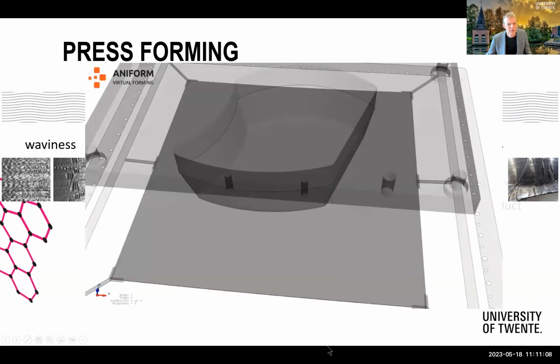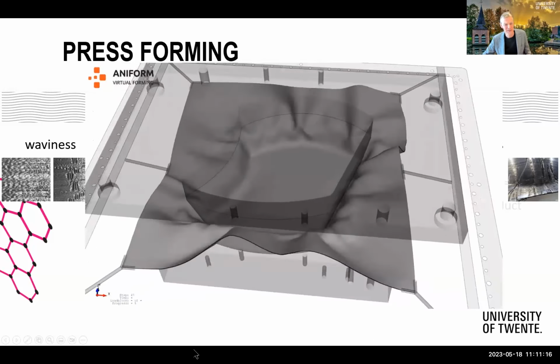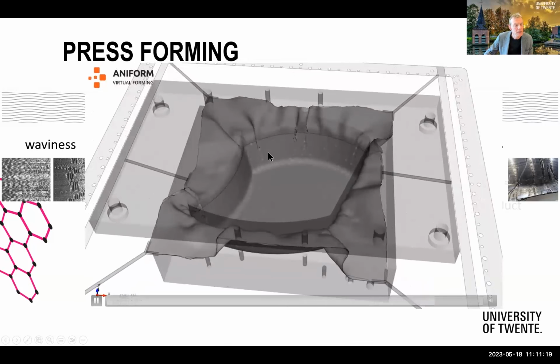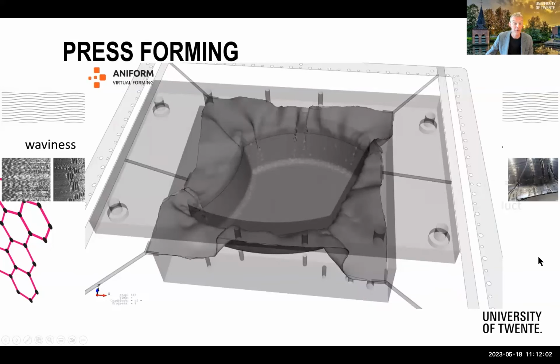Well, of course, that is very much part dependent. So here's, let's say, a fruit basket, a composite fruit basket. You always wanted to have one like these, but here you can obviously see quite severe wrinkles in the flanges of this shape. In forming software, you have the ability to change easily the size of the blank, the shape of the blank, the laminate supports, etc. And you have the relative ease of changing the geometry of your tooling to get a product without these nasty defects, which actually permits using the products you've manufactured with all your efforts.